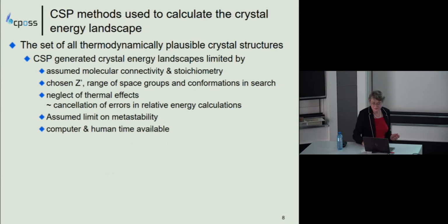So, our crystal structure prediction methods, we'd now say that we're trying to generate a crystal energy landscape, the set of all the thermodynamically plausible crystal structures for the molecule. But that is going to be limited, we know, by what we put into our calculations: the assumed molecular connectivity and stoichiometry. Protons are unlikely to be able to jump if you've got a different tautomer, or you're converting from a salt to a co-crystal. You've chosen how many molecules you've got in the asymmetric unit cell, the range of your space groups.